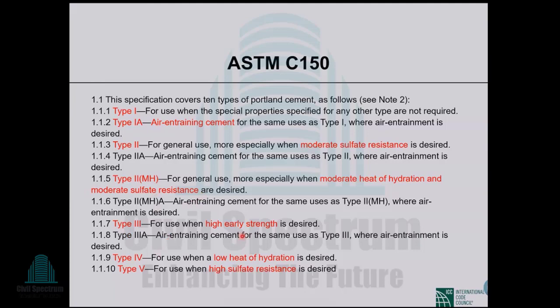Type 3 is high early strength, that is like 52.5 R. In BDS EN, the types of cement like 42.5 R, 52.5 R, you can compare those types with type 3. Type 4 is even less heat of hydration, low heat of hydration, and type 5 is high sulfate resistance cement. So there are different types mentioned in ASTM C150, but the type we use in our country, CEM1, you can compare that with type 1 cement.